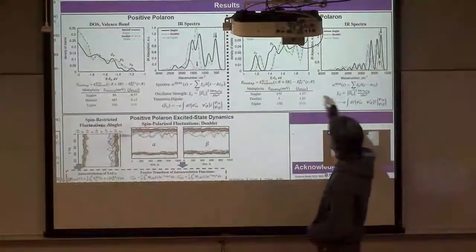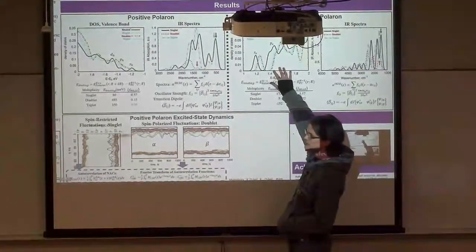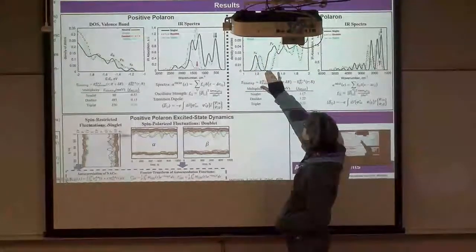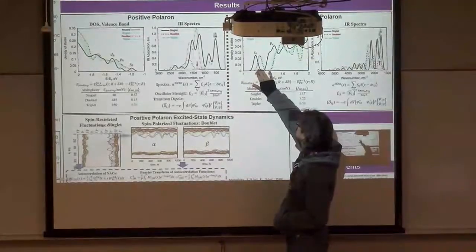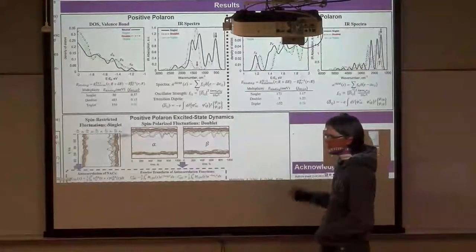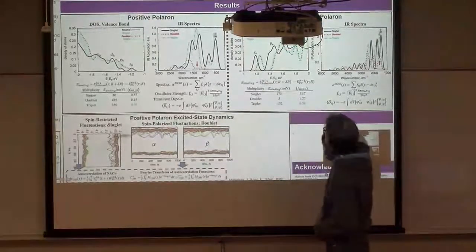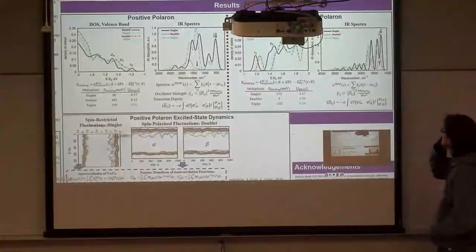So we calculate the valence band density of states. You compare between the neutral ground state model and the polaron model, and we see another consistent shift which widens the band gap of all the states. And then there's not much difference between all the multiplicities for the states.